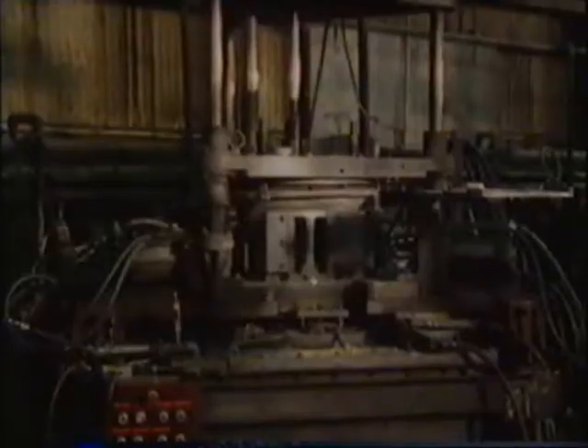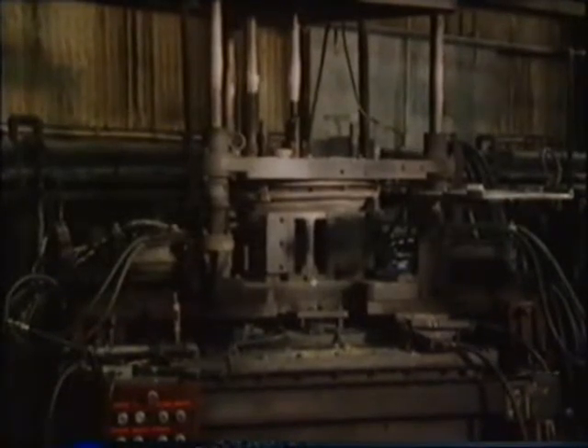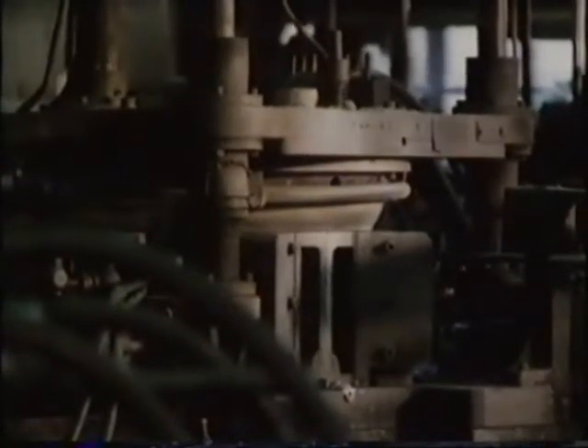A low air pressure, about 6 pounds per square inch, is then applied to the molten aluminium in the reservoir underneath the die. This increase in pressure forces the metal up the venturi tube and into the cavity of the die until it's completely filled. Solidification begins at the edges of the rim and works progressively inwards. When the casting has completely solidified, the die is opened and the casting removed.